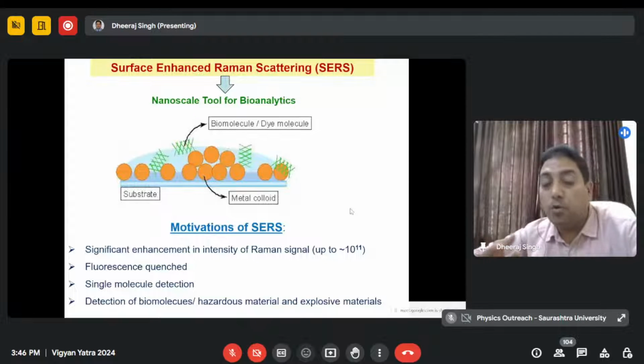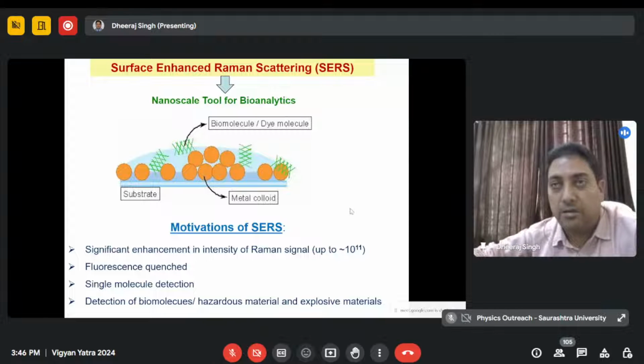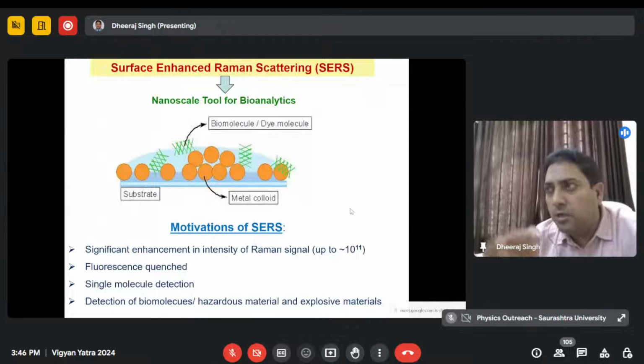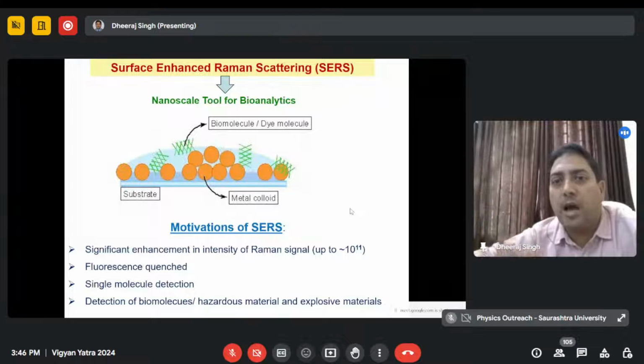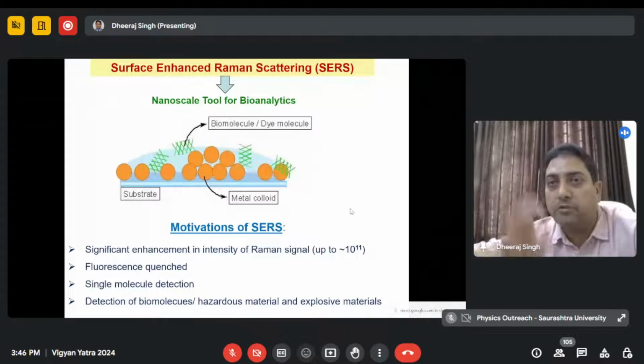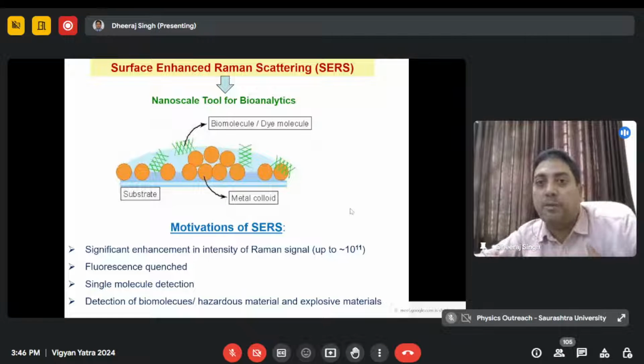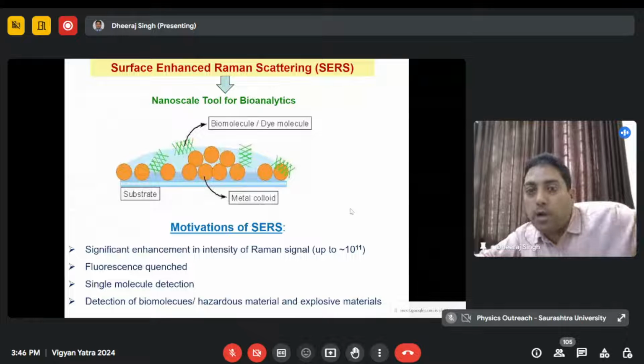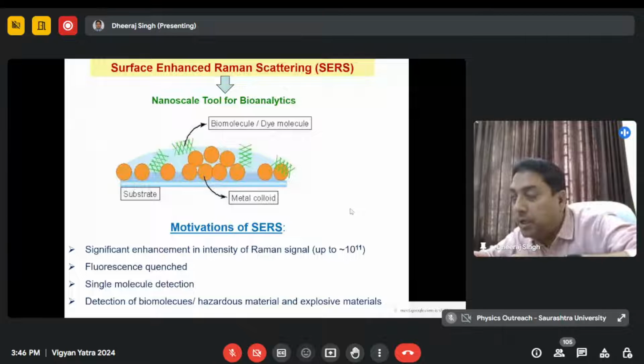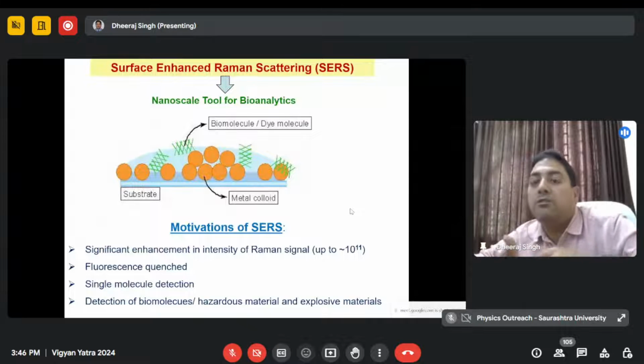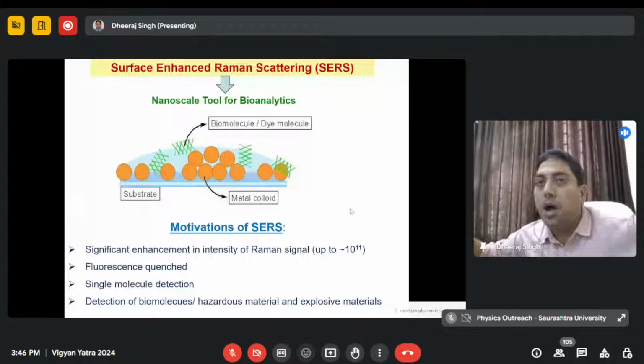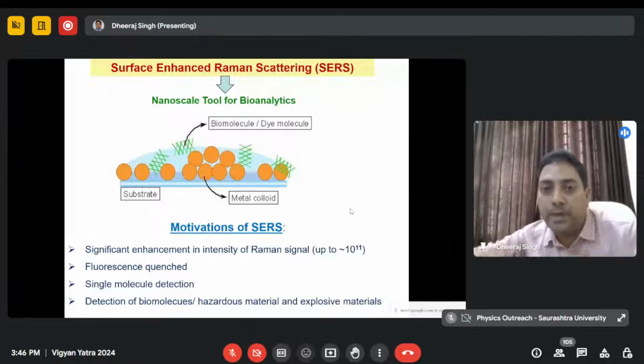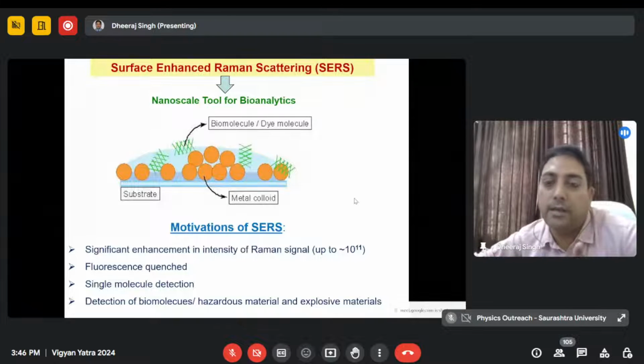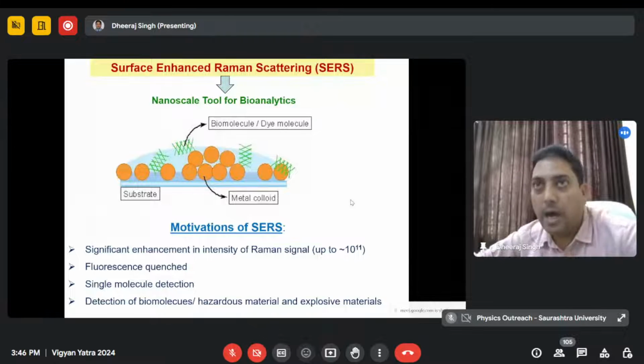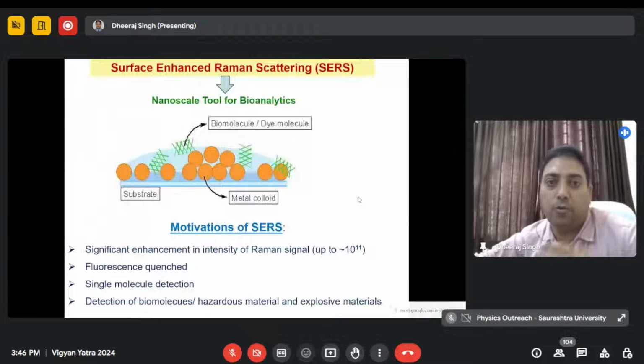So what happens if your explosive element like RDX or TNT is there in only 10 to the minus 12 mole or nanomolar concentration on any particular surface? Now you can make a nano substrate, a nanometal substrate. You can put only one drop or one dust particle of TNT on that nano substrate. This nano substrate will enhance the signal of that particular molecule, and we can detect by certain peaks observed whether it is TNT or RDX or another explosive element.